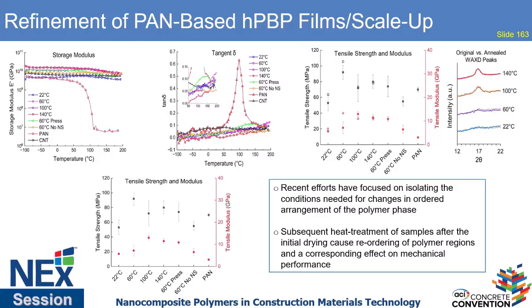So here, this is dynamic mechanical analysis. You can see the black line represents the pure nanotubes, but all of the composites that we've treated, essentially you can't see the polymer. It's almost like there is no polymer there. And that's because the polymer is not behaving differently from the nanomaterial, because when they're blended like this, they're perfectly interacting with one another. We can also see this again in the tangent delta curve. You can see the red is the pure polymer, so it's got this nice tangent delta. The polymer is in all its other films, but I cannot see it.